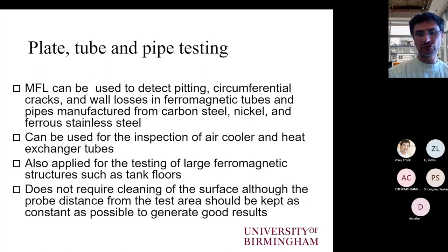The majority of the applications, of course, relate to plates, tubes, and pipes, as I mentioned earlier. And it is very common to inspect air cooler and heat exchanger tubes using this method. So we push the magnetic flux leakage probe through the tube, and then as we retrieve it, we take the measurement and we look at the signals in order to see whether there is any pitting or general corrosion or erosion that has affected these tubes. The same can be done for pipes, but it is also feasible to do the inspection from the outer layer, provided that the wall thickness is not excessively great.